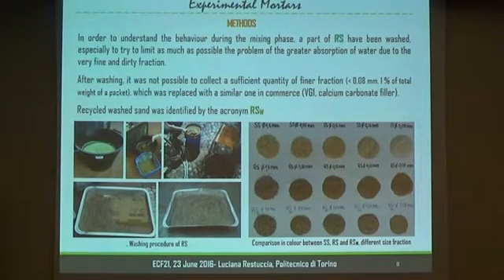We know that there are workability problems, so in order to understand the behavior of our mortars during the mixing phase, a part of the recycled sand was washed to try to limit as much as possible the problem of the greater absorption of water during the mixing phase due to the very fine and dirty fraction of recycled sand.